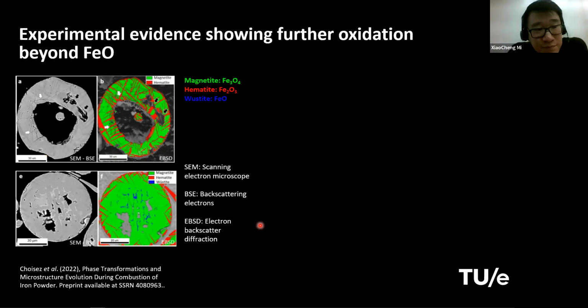So these completely burned particles show that there's no iron left at all. That means it's definitely completely oxidized. And you can see that most of the particle is converted to Fe3O4. And maybe in this case, there is a tiny bit of FeO left in the middle. And near the surface, you also have some even further oxidized product, Fe2O3. But we know that Fe2O3 can only be stable in solid phase. That means before the particle gets solidified, the whole particle is nearly converted to Fe3O4. So this actually supports our hypothesis that we shouldn't stop the reaction at FeO in our model, right? If you stop there, then that contradicts the experimental evidence.